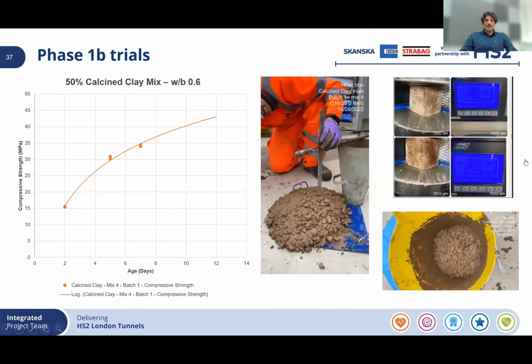Next slide, please. What we were very excited to find, though, although we were targeting 20 megapascals at 28 days, this is a recent result from one of our recent mixes. We achieved 35 megapascals at 7 days, and that is a mix with a water binder ratio of 0.6 and 50% calcined London clay. So this is quite, I would say, surprising, and it is reinforced from other mixes and mix results that we have produced. So it's not an outlier. We got very promising results.